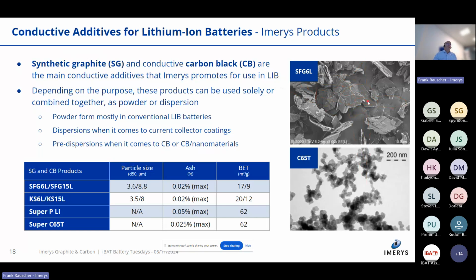If you look at the SEM image here, you see that the synthetic graphite is very high aspect ratio graphite, so very thin, flaky particles, and our material is very anisotropic, but it works very well as a conductive additive, being used at 2 or 3% or 4% in the anode formulation.